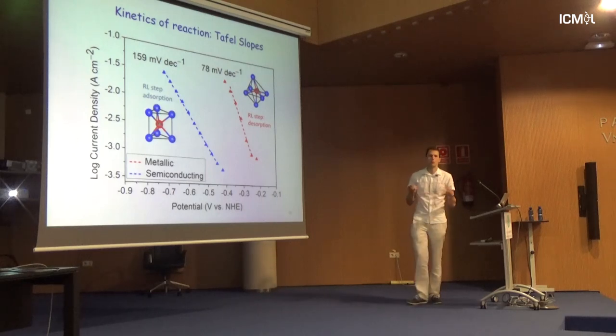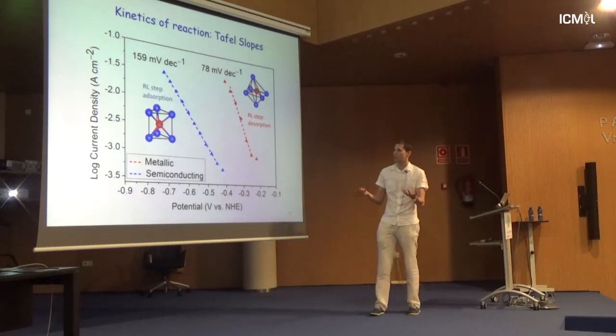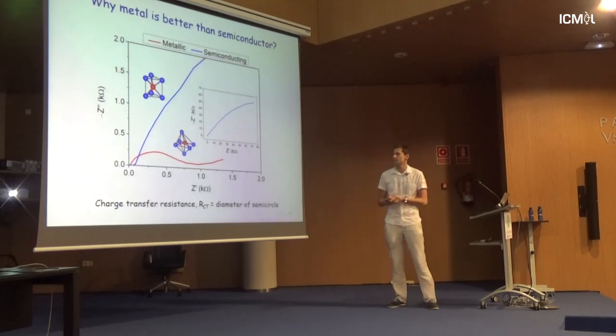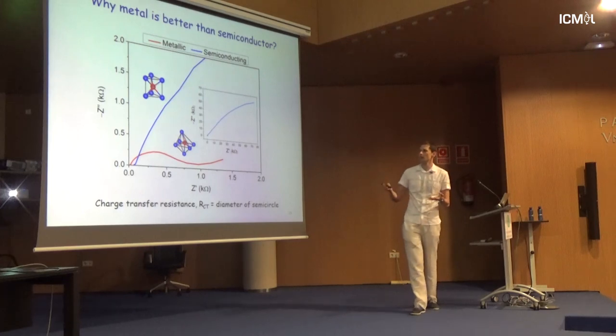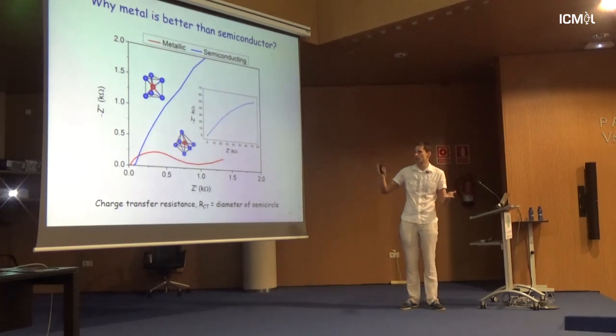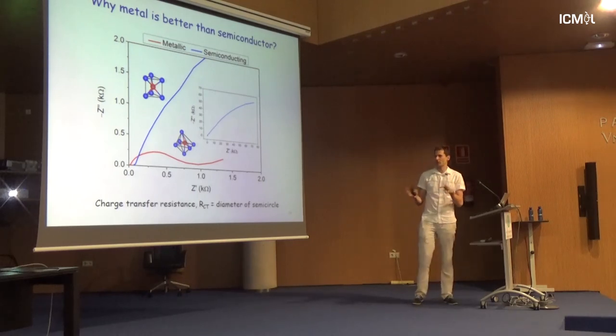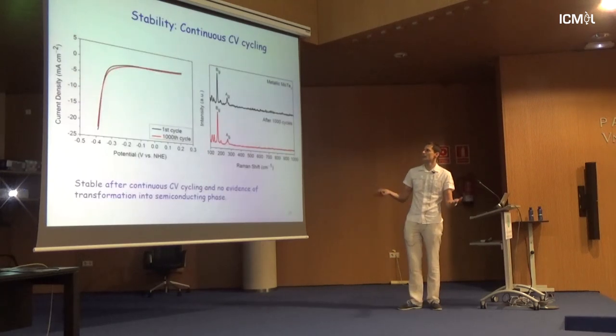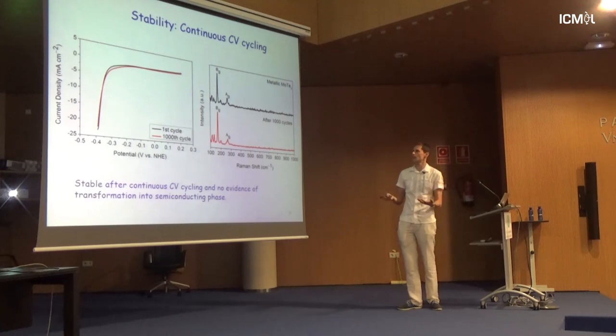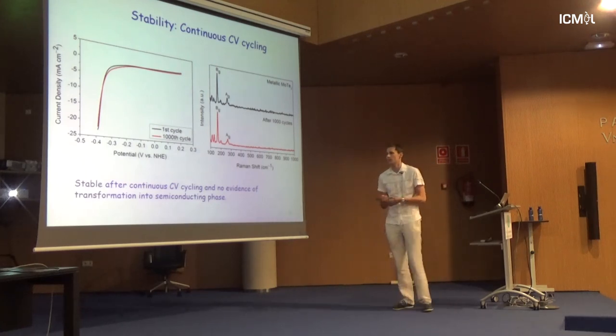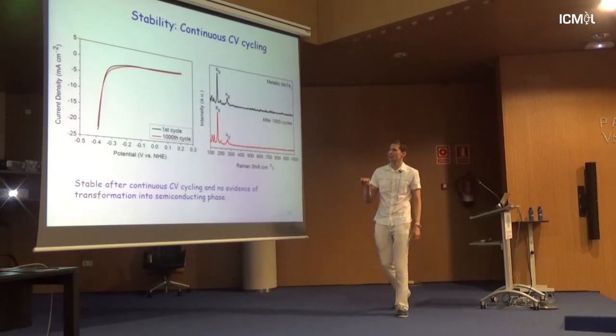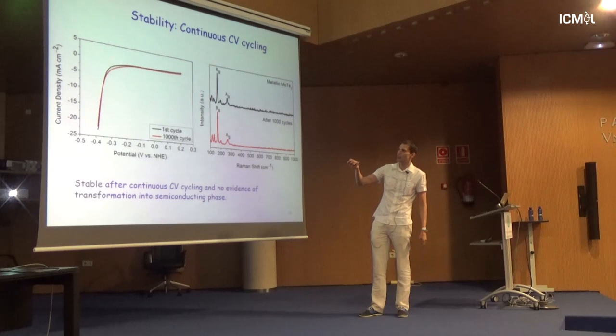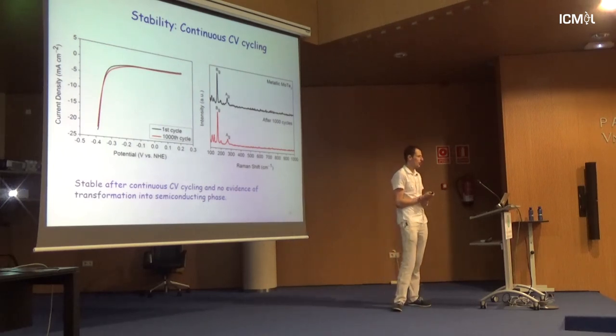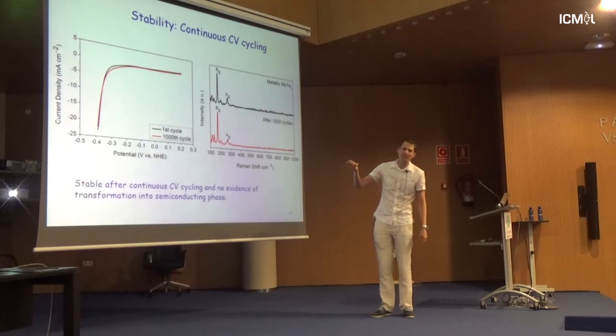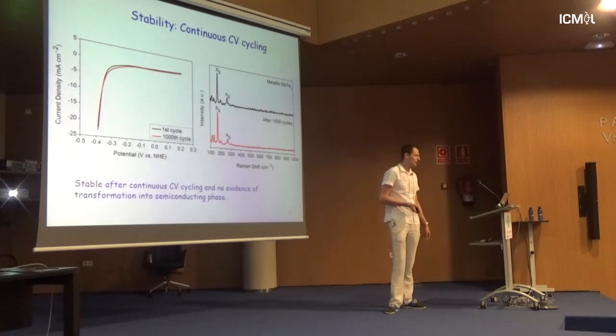But what is very interesting, by changing the crystal structure, you can obviously change quite a bit. And they're also obviously different in terms of where one is metal and the other is semiconductor. So this is charge transfer resistance, which could be a good approximation of conductivity. And stability, so you run it for continuous cycling, so you can do many, many cycles, and then you see. But what was very interesting, we say that it's stable, so there's nothing changing, but my students were not really convinced, and they said, well, you see, after 1,000 cycles, it's kind of getting better.